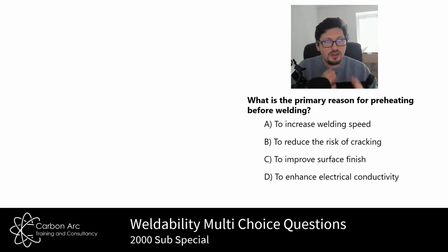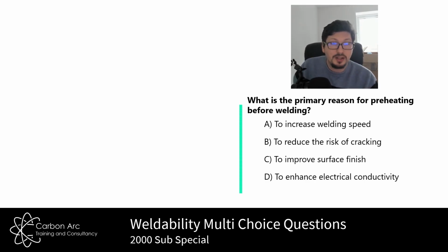So slowing the cooling rate, if we think about a TTT diagram, is going to push us into the pearlite, ferrite, and cementite regions. We don't want to get into martensitic regions. So preheating adds heat, which slows the cooling rate. That can be helped if we then add blankets on top of things and try and keep the heat in for as long as possible. But by slowing the cooling rate, by keeping away from the martensitic regions, we are going to reduce the risk of cracking. Yeah.